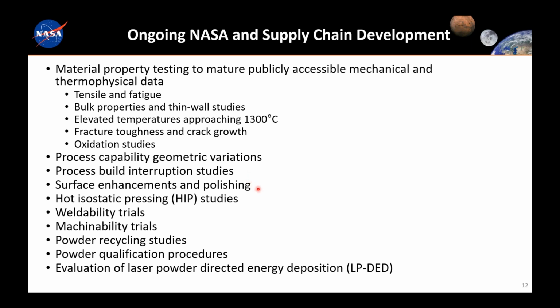The surface enhancements and polishing, and then we have plans to publish future papers on hot isostatic pressing. What is the optimization of the HIP cycle that we would use and recommend for the GRX 810? Weldability trials, machinability trials, powder recycling, powder qualification procedures, and then, as Tim mentioned, evaluation of the laser powder DED process. So all of these are in work at some level, and again, be on the lookout for future publications for each of these attributes, as we mature this through the entire supply chain.